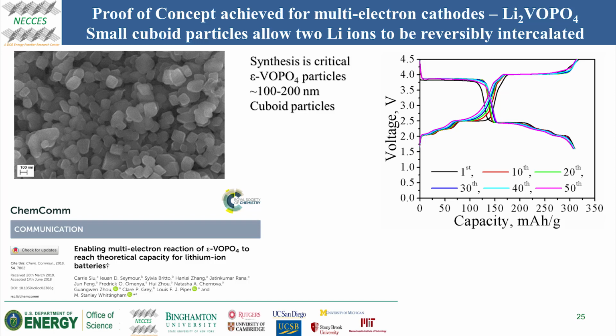And this is what we call cuboids. We make these 100 to 200 nanometers in size. And on the right-hand side, you can see the cycling behavior we had in these materials. The 5+ to 4+ is about 4 volts, and the 4+ to 3+ is about 2.5 volts. If you look closely, the black curve is the first cycle, the purple one is the 50th cycle. If anything, it behaves better on the 50th cycle than the first cycle. So we had proof of concept. You can put 2 ions into a crystalline lattice without destroying that lattice.